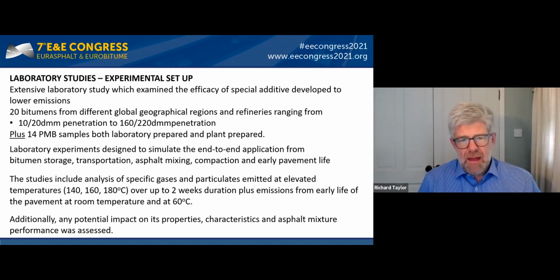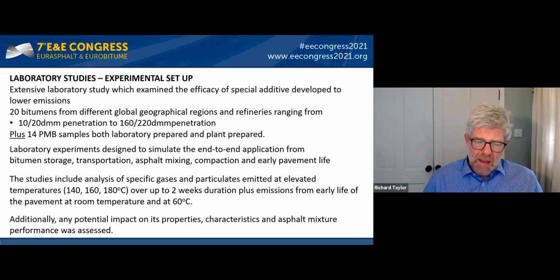And so we looked at the range of temperatures for the hot part of the cycle, so 140, 160, 180 for the storage, transportation, mixing, compaction. And then we looked at 60 degrees, which we thought was representative of a pavement on a hot summer's day for the emissions from the finished pavement. And then, of course, we looked at the traditional: did it have any impact on the specification properties and the characteristics of the bitumen and the asphalt?